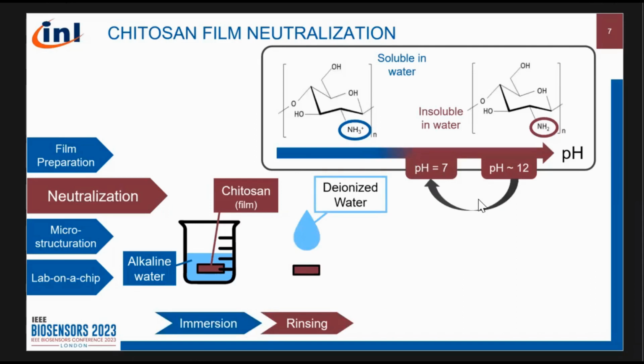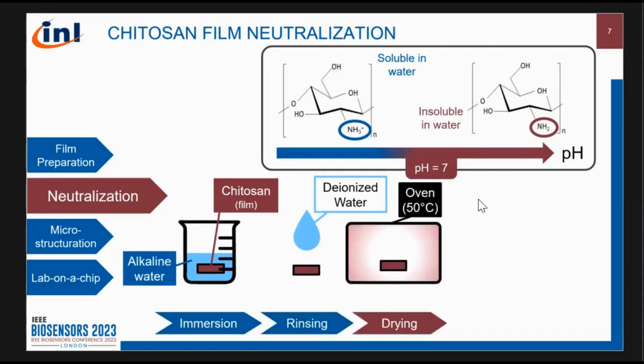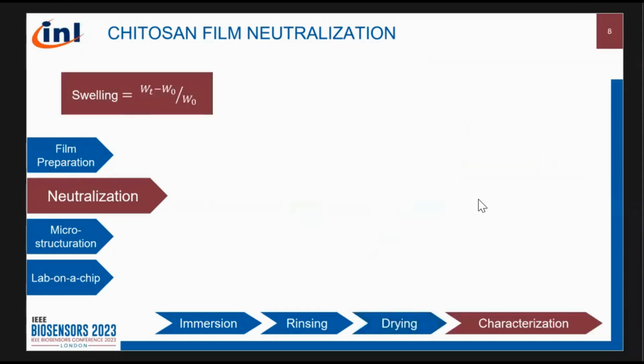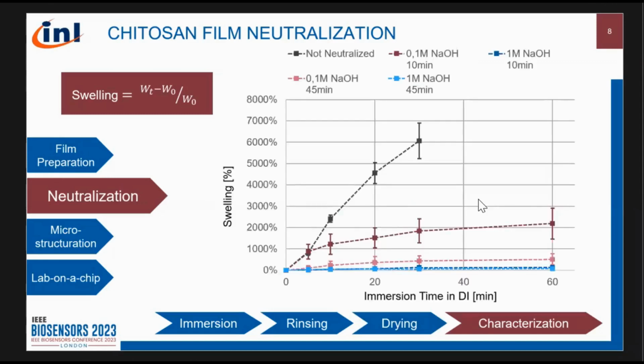Then the film is rinsed to remove any molecule left. And finally, it is dried once again to obtain a film. Now, if we want to characterize the properties of the different neutralization methods, we measure the swelling of the film, how much water it absorbed, by comparing the weight of the film when it's dry with after spending some time in deionized water. So here you can see, depending on the time spent in water, the swelling of the film.